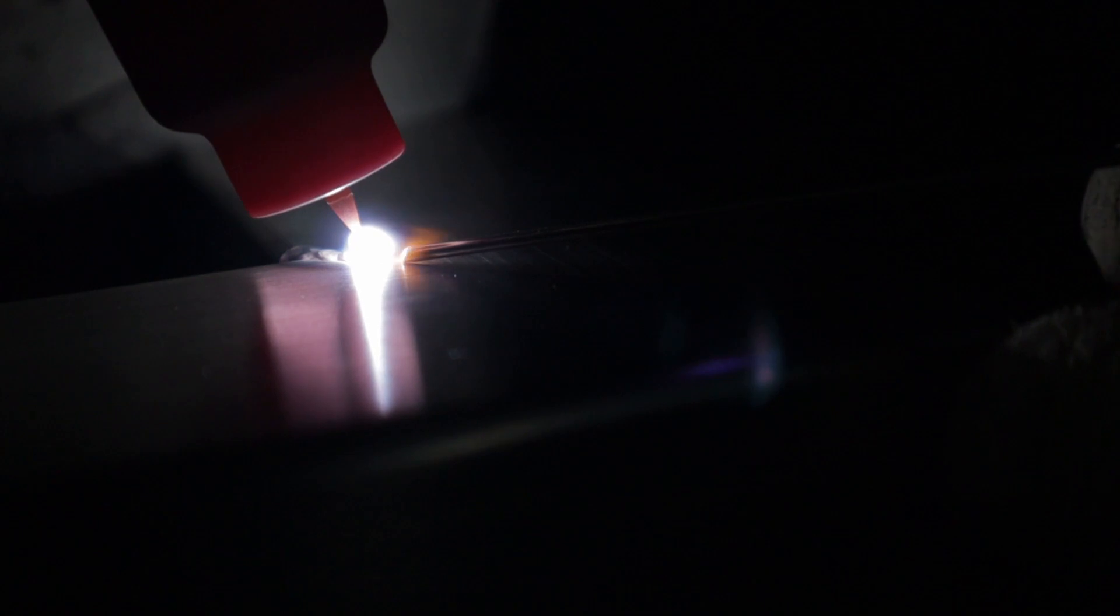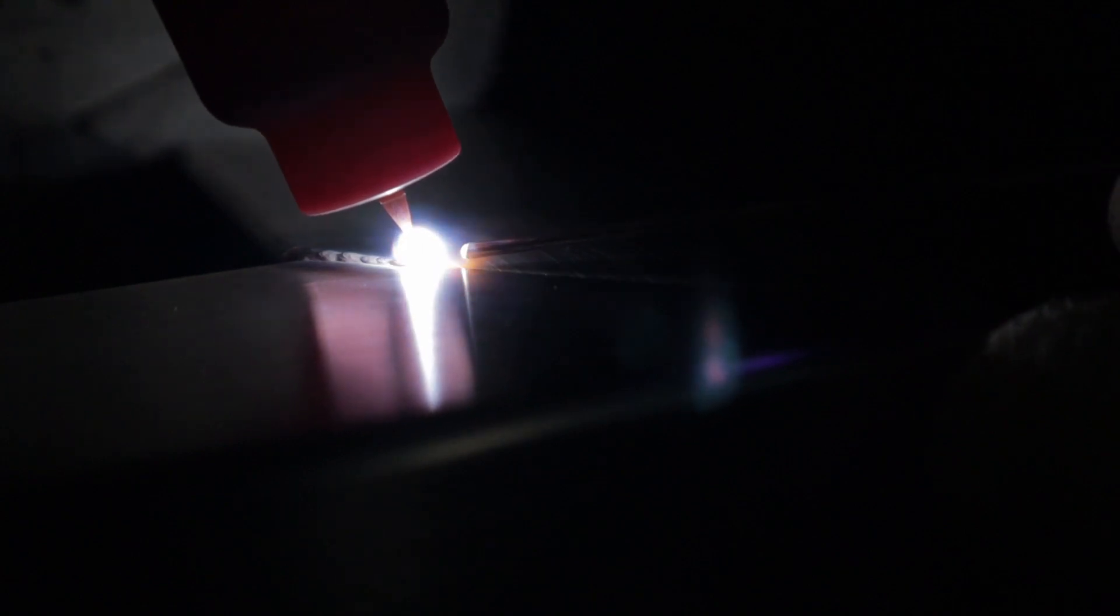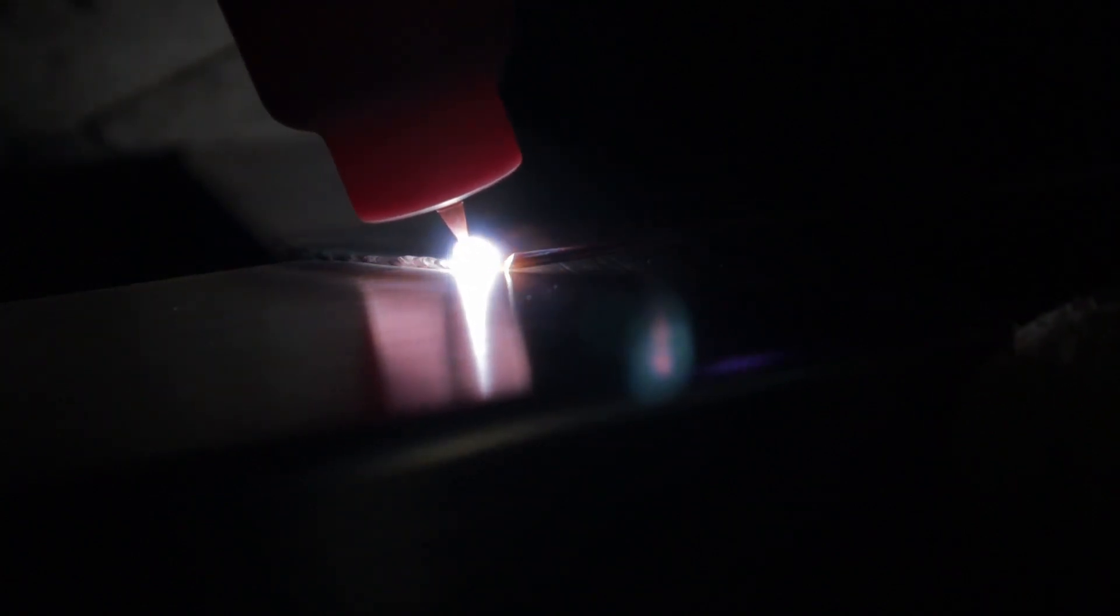For the next example Sparky is set at 25 amps. It's easy to think I have the welder set lower so I can get the hang of welding. When you start you have a lot going on feeding the wire arc length and stuff but the weld pool is taking too long to become the ideal size and when I add the wire it just drops a huge blob into the weld cooling it down again.